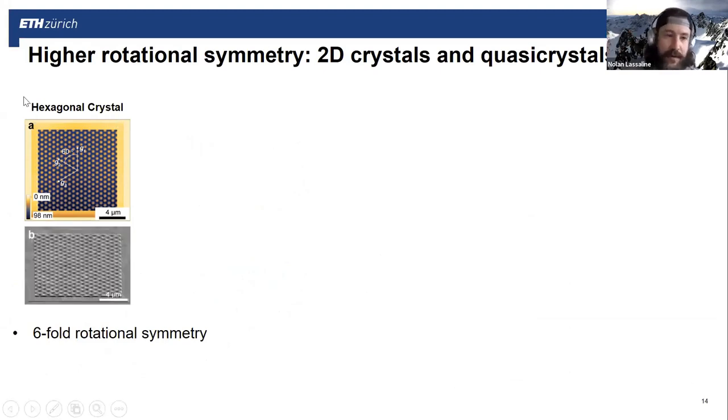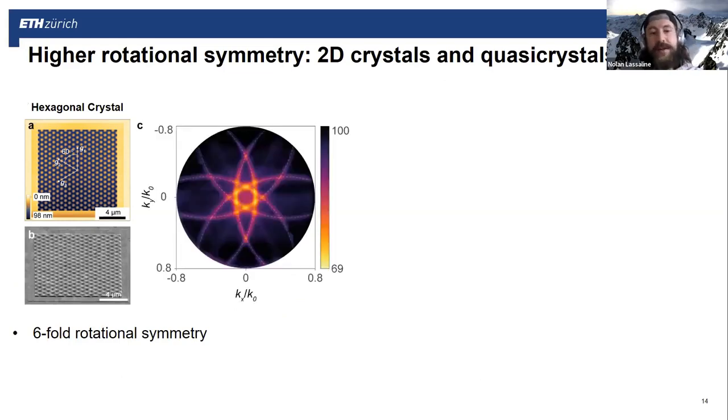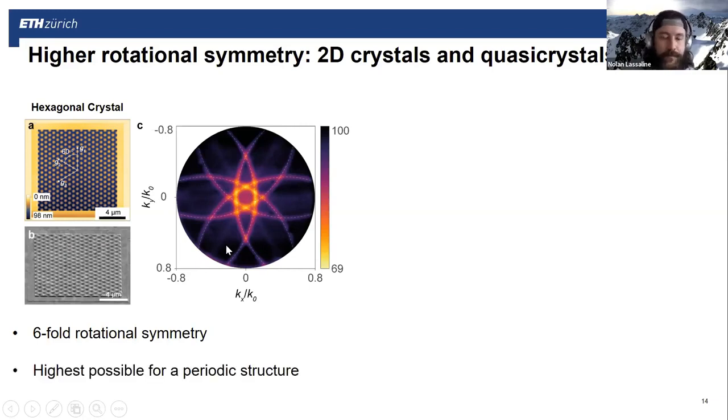And of course, we can transfer that to a metal surface. And again, when we measure the optical properties of the surface, we nicely see that this diffractive profile also has this six-fold rotational symmetry. And again, these dashed lines are calculations of what we would expect, and we see a very nice agreement between the two.